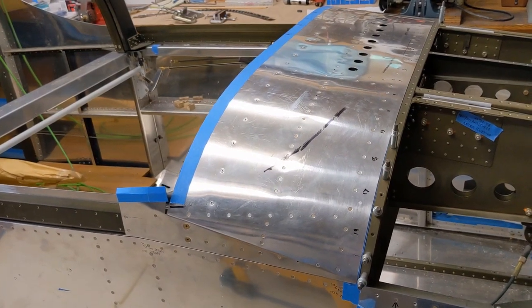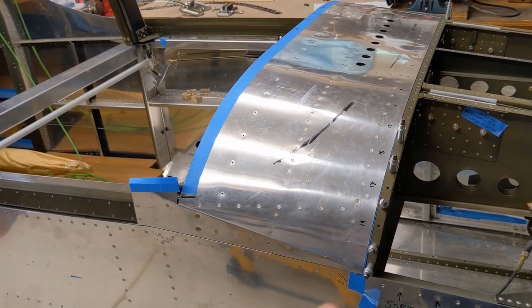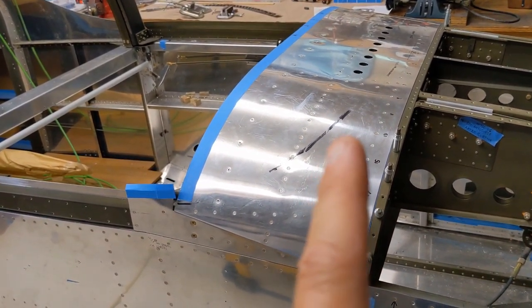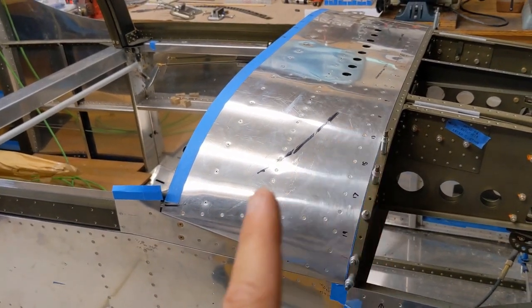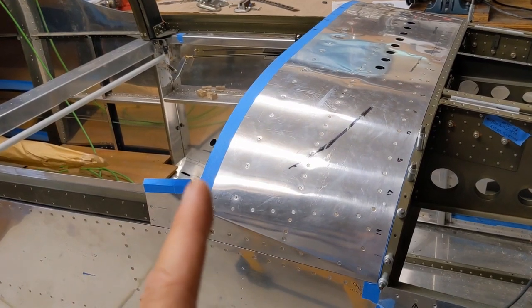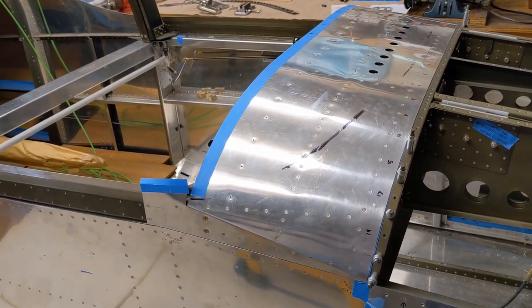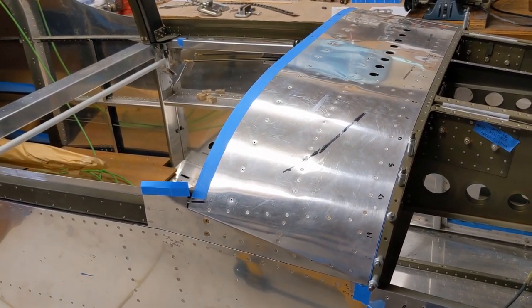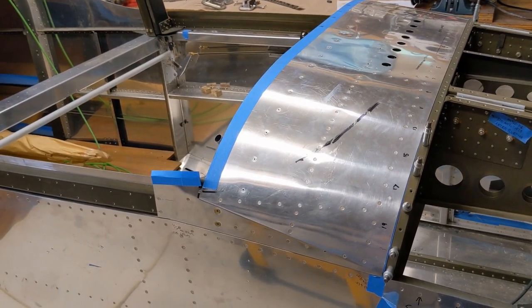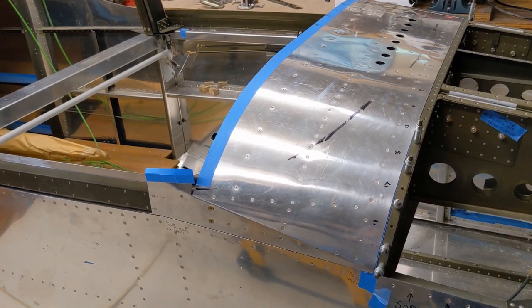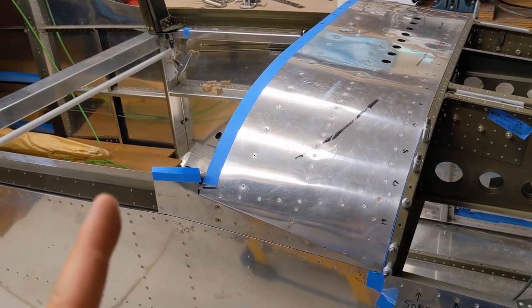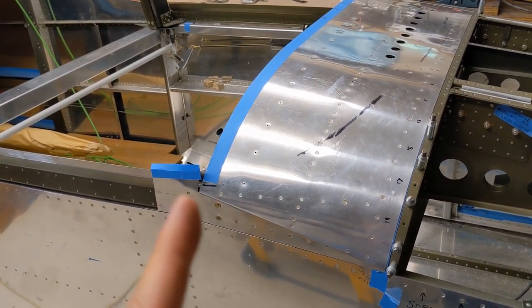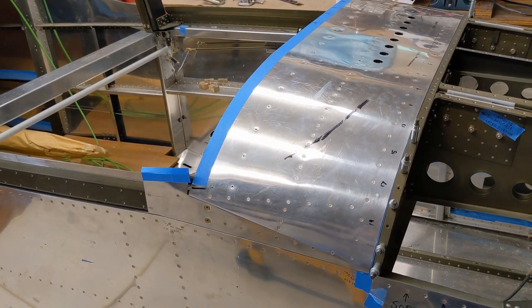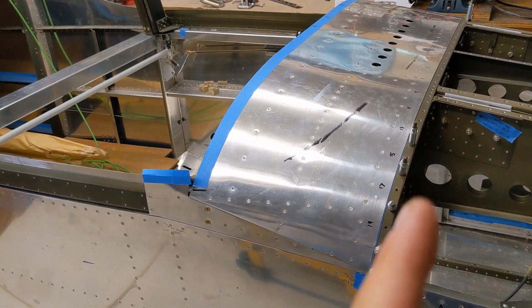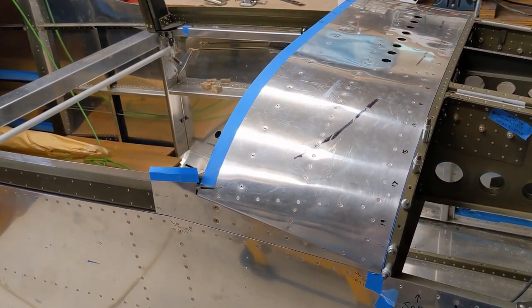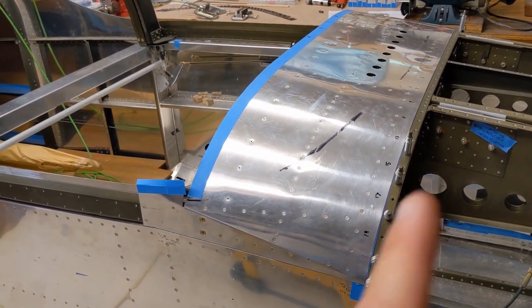when a structural element like the canopy is attached to another piece of structure, and there ends up being a large transition in stiffness, say from a fiberglass attachment to Sikaflex attachment, then it creates a stress riser right here on the canopy. And I've only heard of one Sikaflex canopy that developed a crack, and that crack was basically coinciding with the joint here. Now that could have been a function of the attachment of the side rail to the canopy frame with the little joint plates, but it also could potentially have been contributed to by a difference in attachment rigidity. So just to avoid that, I'm just going to be using Sikaflex all around.